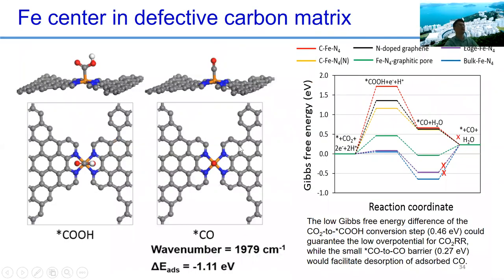Lastly, we did some testing to see whether there's a defective carbon matrix, so that means there are not perfect carbon rings here. For the reaction involving COOH and CO, we can also calculate it. The adsorption energy is much lower, and the wave number we can predict is very similar to what we observed. The reaction pathway is the following green one. For both the first step and the last step, the energy needed is much lower than in the previous cases. So we believe that the real active site can be this defective iron center.